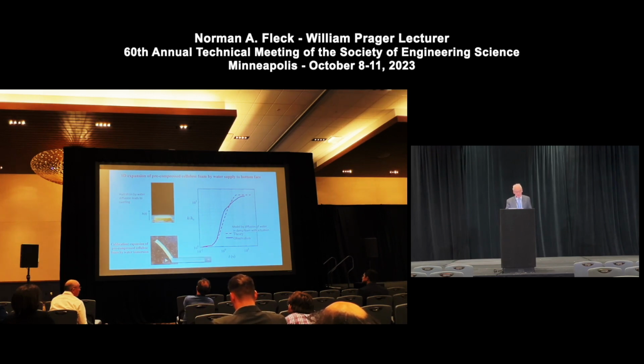But in order for the water to get to the foam, if the foam is not small but it's a larger specimen, then, in this case I'm putting water in the bottom of it, water has to diffuse in, it has to migrate through the foamed state, so we now have damp foam in this region, and when the water reaches the dry foam ahead of it, it expands. So you see this process is one of diffusion of water through the damp foam, followed by the actuation, as I'd shown in this image below.